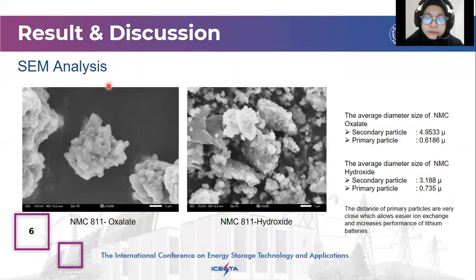Okay, the bonding groups on the material have been identified by FTIR analysis. Then the material is characterized by SEM to determine the shape and size of the constituent particles in NMC 811. SEM characterization uses a magnification of 10,000 times on the sample. In the same analysis, two particles were obtained: primary particles and secondary particles. Primary particles are constituent particles with a small scale, while secondary particles have a large constituent scale.